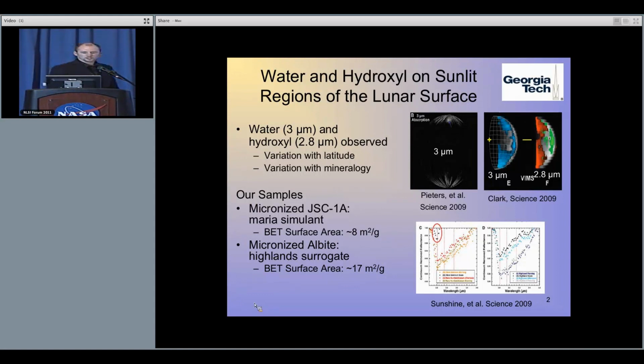We're still working on getting actual lunar samples, so thus far we're using the micronized JSC-1A. When I say micronized, I mean we actually put it in a micronizing mill and ran it for a while to break up the particles. The idea is to activate the surface a little bit and make it more like the actual lunar regolith. For the highlands, best sample we could get our hands on so far is micronized albites.